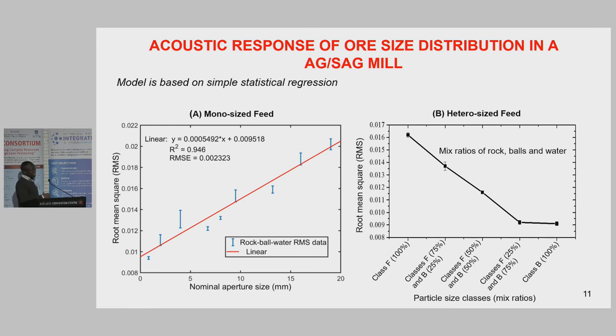In terms of the different ore size distributions that we investigated, it was observed that the acoustic response increases with increasing size fraction. So when there's a sudden change in the size of the feed, there is an increase in the mill acoustic intensities. Also, to my right, for the blend ratios, where we considered a relatively coarser feed size fraction and a finer feed size fraction, we saw that the mill acoustic intensity or energies reduce considerably as the concentration of the relatively finer feed size fraction was increased. This clearly indicated that the acoustic emission response was affected by the blend ratios of different feed size fractions.